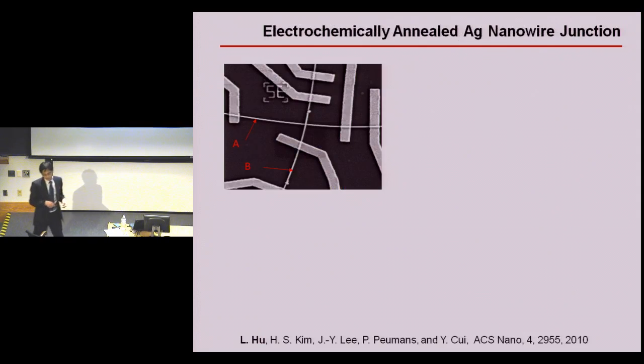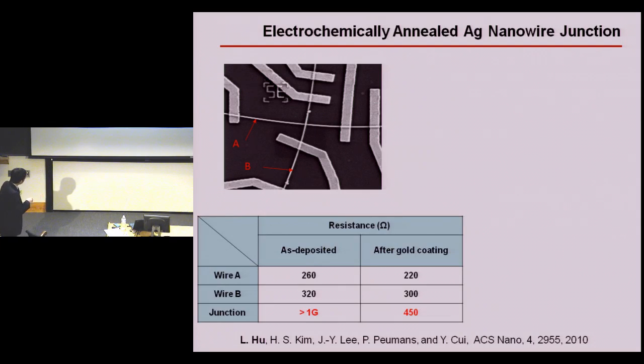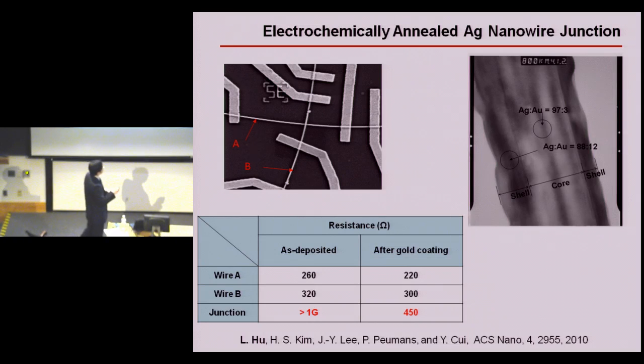So in the end, we will fuse the two junctions together through this replacement. Let's look into some details here. I did the measurement for the transport property of two wires as well as their junction. You can see here, the junction resistance was larger than 1 gigaohm before this electrochemical annealing method. And after that, the junction resistance decreased dramatically. And looking under the TEM, you can see that after the electrochemical reaction, there is gold inside the silver nanowires. So both these two measurements confirm this electrochemical annealing method is effective in reducing the resistance of the wire junctions.